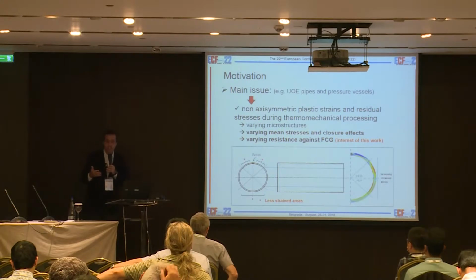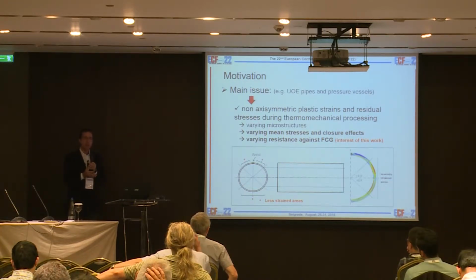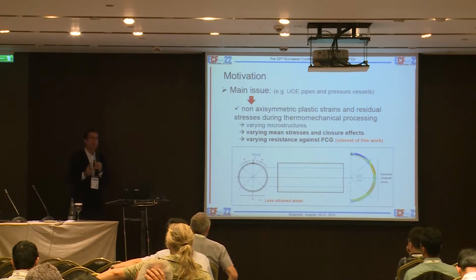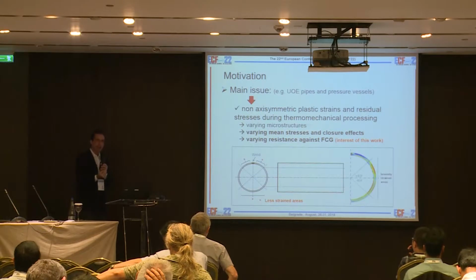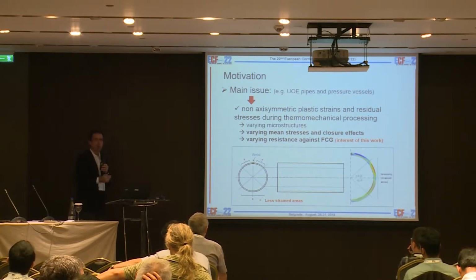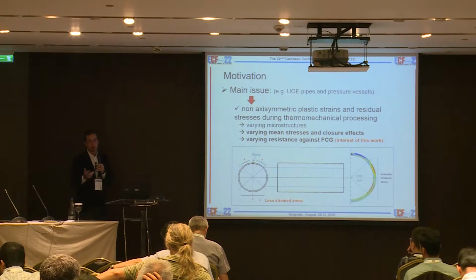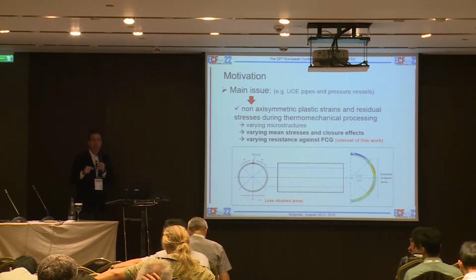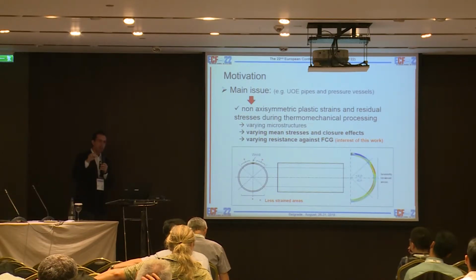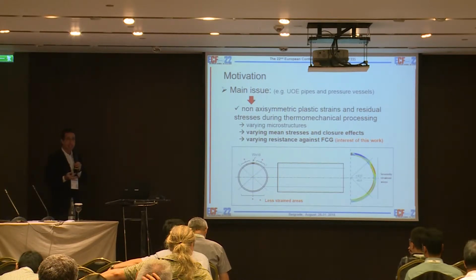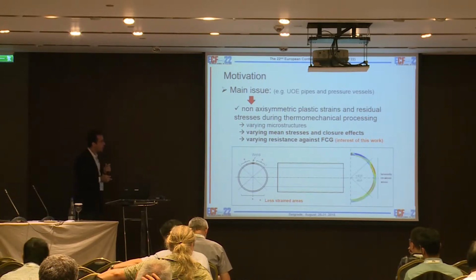Gustavo, why did it start? It started because we could not validate some calculations we were doing regarding fatigue crack growth. The values were not coherent. We realized that an extra effect was probably included in the problem, and finally we detected the problem was related to residual stresses measured by X-ray diffraction and the hole drilling method using strain gauges, and then we started studying it on a numerical basis in a more structured manner.